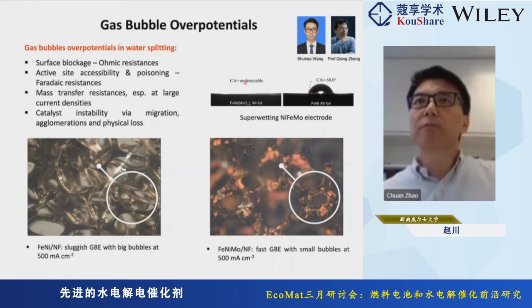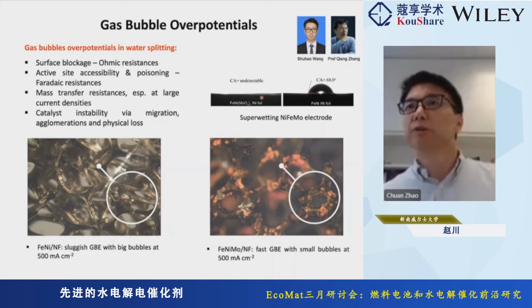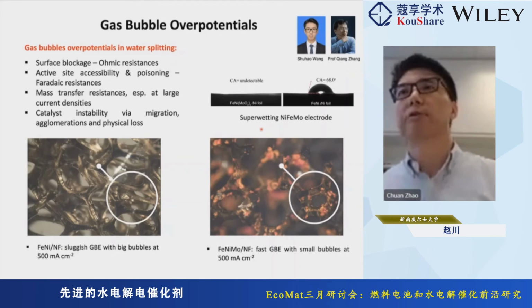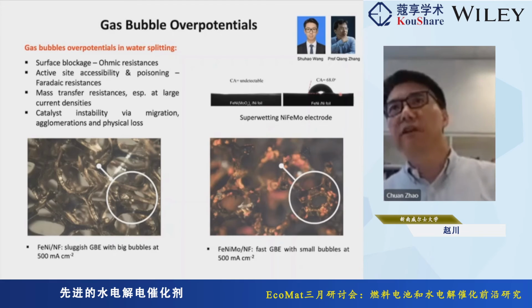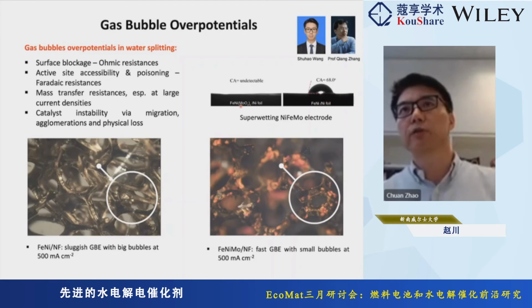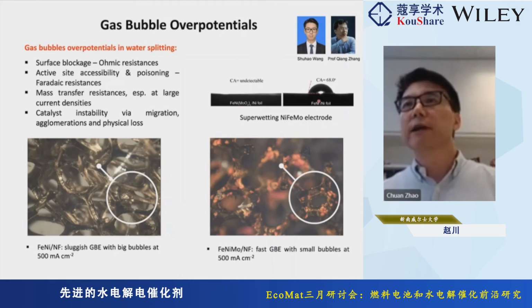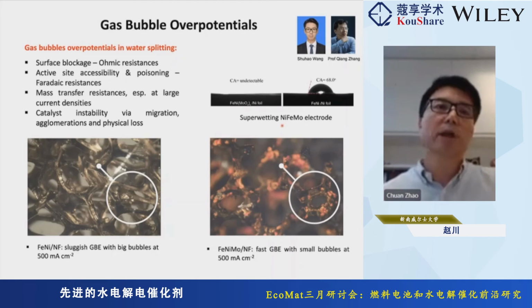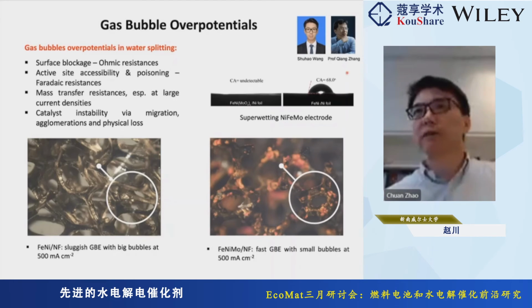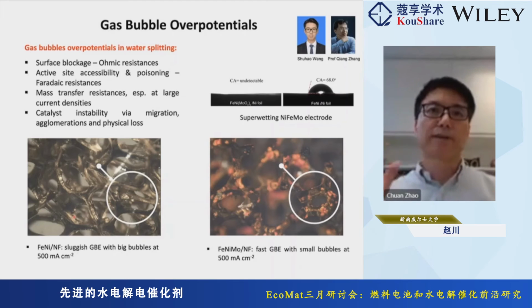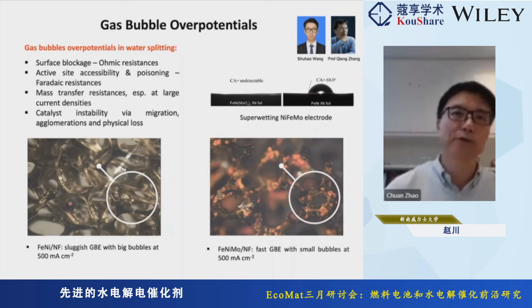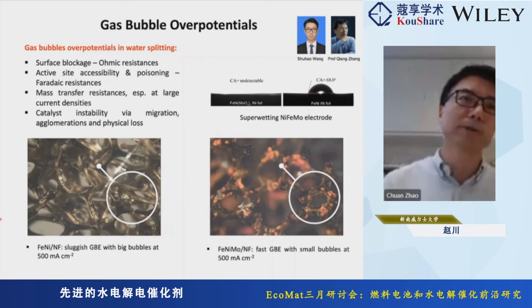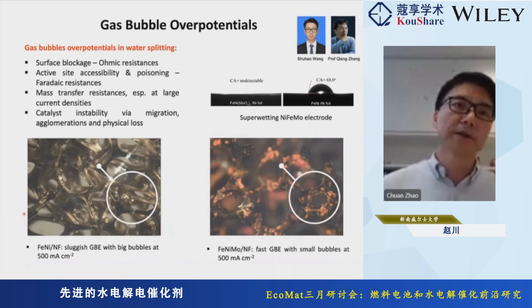So by introducing the molybdenum into the nickel iron system, we can tune the surface wetting property of the electrode significantly. We can see from nickel iron to nickel iron molybdenum, we actually get a superwetting electrode surface. So with the help from collaborators using their advanced microscope, we were able to record this gas bubble evolution dynamics in a sort of, let me see if I can play this.